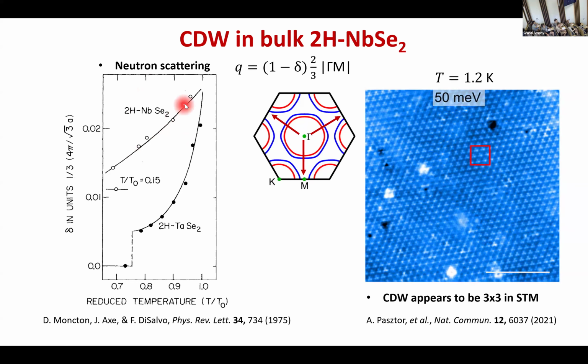They just observe this phenomenon. And from STM, people also see directly these charge density wave. And the charge density wave basically means that along the lines of the atoms, this is just selenium atoms, either every 3 atoms you have one brighter atom. So this actually corresponds to somehow like 3×3 CDW. So it looks like commensurate charge density wave, but actually it's not.